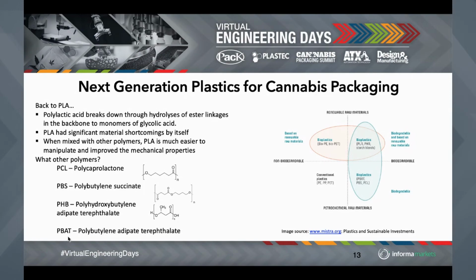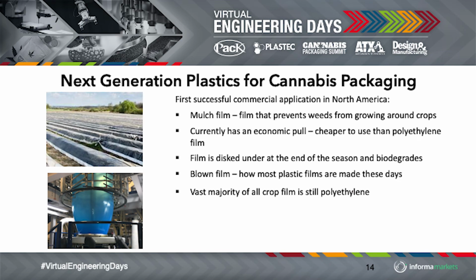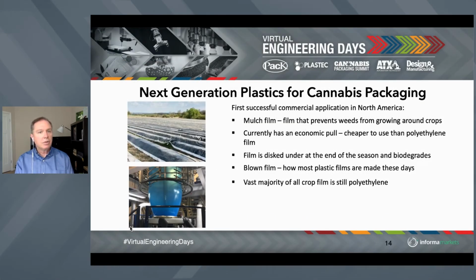So if you look at commercialization of these types of materials, the biodegradable materials within North America that have significant commercial success is what's referred to as mulch film. And mulch film prevents weeds from growing around crops. For example, if you go out to a strawberry field or other fields that have these types of things to prevent the weeds from growing there, a lot of that mulch film that you see there is polyethylene based. So it's still made from polyolefins. However, it's becoming more prevalent that it is going to bio-based materials. And the reason for that is that it actually has an economic pull. The bio-based materials overall are cheaper to use than the polyethylene film.